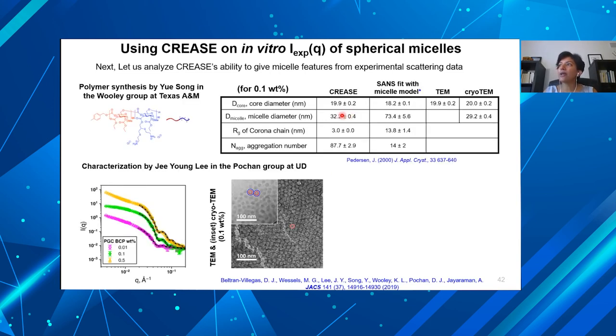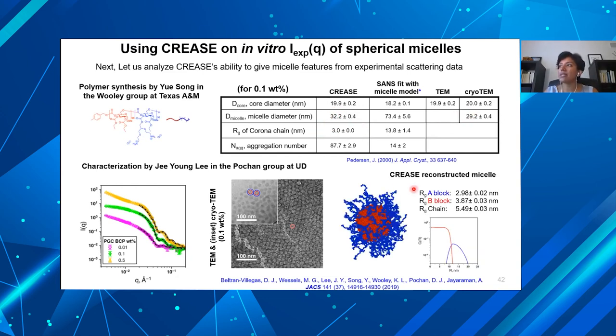If you look at CREASE, now the numbers start to get closer and closer to cryo-TEM. The radius of gyration that we got from the second step, that also agrees really well if you take the micelle diameter and the core diameter. How big could the chains be in the corona? That is in good agreement as well. And so is the aggregation number that you can back calculate from the density.